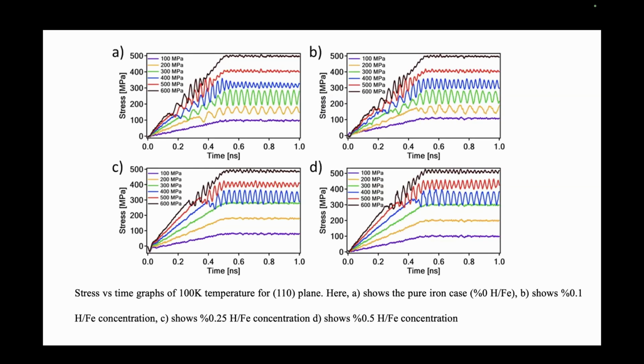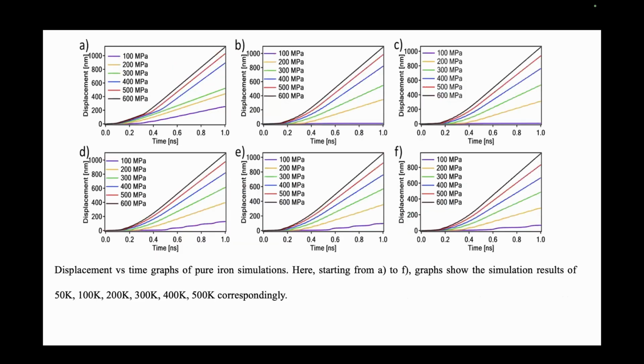We didn't use a unit step function when applying the shear force. Basically, for 0.5 nanoseconds we increase the stress, then the stress becomes steady, just so as not to create shock waves in the lattice. So this is the way we input our shear stress. This is just one example at 100 Kelvin for pure iron with different hydrogen concentrations. Then we observe the displacement versus time graphs. Once we increase the stress, of course, we get more displacement. Once you take the first derivative of displacement, you get the velocity of dislocations.